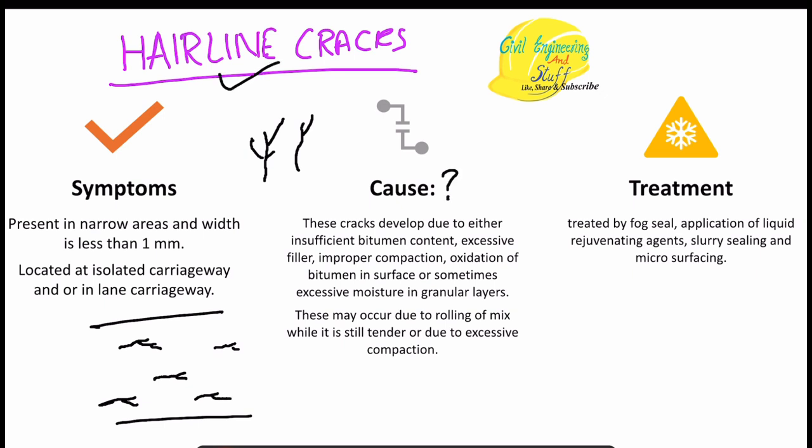What is the cause of these cracks? These cracks develop either because of insufficient binder content, excessive filler use, inadequate compaction during the laying of the surface course, excessive intensity of oxidation of the bitumen, or ingress of moisture in the granular layer.